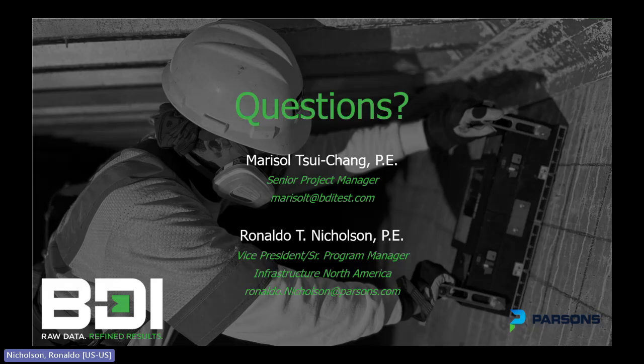Again, what we found through the research and Dr. Sanchez, is that over time, the phenomenon of expansion would continue in perpetuity and continue to deteriorate the concrete substrate unless there was a pressure that basically stopped that gel from expanding. That pressure through research is 5 megapascals or 725 psi. So we're looking to exert that through the encapsulation system, both the concrete and the post-tensioning system.